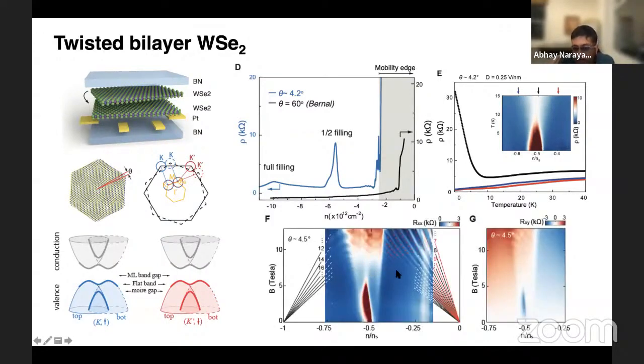We can also measure magnetotransport, so we can put this in a large magnetic field. If you do that, you see nice Landau level quantization at high field. And this is very useful to tell us exactly what the filling is. So we know that this point is precisely half filling of the Moire unit cell. And also the Hall effect tells us about the sign of the carriers.